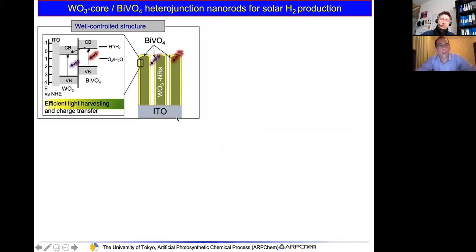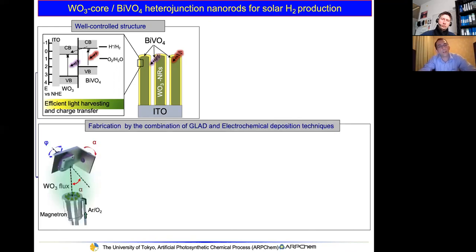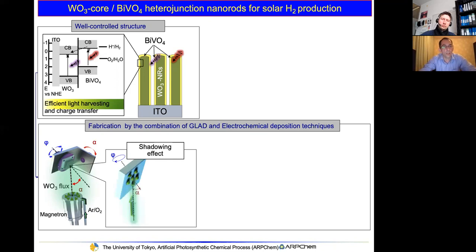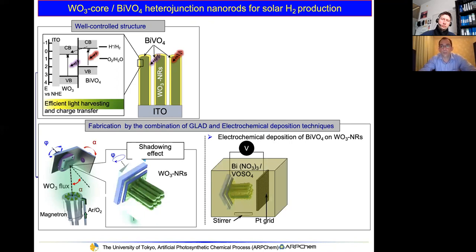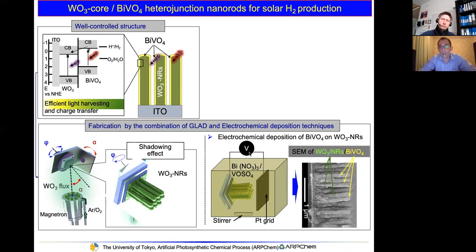Okay, and the next slide, this is again tungsten oxide core bismuth vanadate heterojunction nanorods for solar hydrogen production. We started to fabricate this photoactive material by first using the GLAD system to fabricate tungsten oxide nanorods, followed by electrochemical deposition of the bismuth vanadate. Here are shown the optimized samples. What we can see here very nicely are the vertical tungsten oxide nanorods, and a very thin layer of bismuth vanadate. And this bismuth vanadate was deposited like nanoparticles.